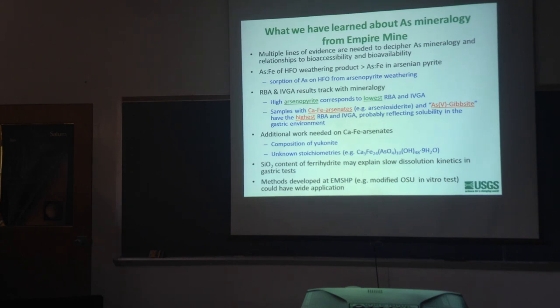When we look at the iron concentrations of the samples that have been submitted to the in vitro tests, the gastric leach tests, we're getting very low iron. But if you were to put iron oxides in pH 1.9, they should dissolve. The mineral is supposed to be soluble. But the kinetics of dissolution, if you only have 1 hour to do the test, because that's the average amount of time that material's in the stomach, that silica basically armors the iron oxide and it will not dissolve that much in that hour, even at body temperature and the low pH. And so that may have a lot to do with the fact that the arsenic is not bioavailable from the ferrihydrite, even though it's probably the main mineral that hosts arsenic in these samples.